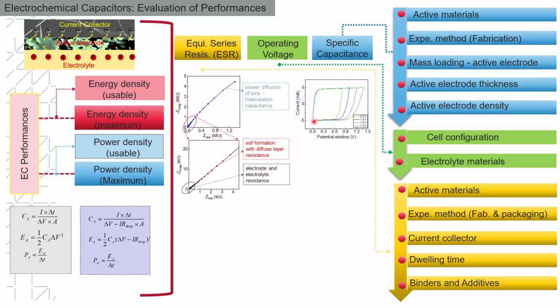Okay, so we evaluate the supercapacitor performance using electrochemical impedance spectroscopic analysis, where you draw the Nyquist plot or Bode plot, or whatever impedance data you observe, and you can find that depending on the type of electrolyte interaction, the resistance of the material will change. That resistance depends on the slower diffusion of ions or the electrochemical double layer formation, which you can clearly determine from the impedance analysis. The equivalent series resistance you can also calculate from the Nyquist plot, where the intercept is.